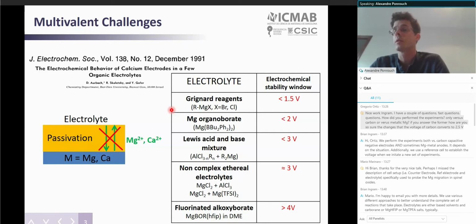And since the first generation of magnesium-based electrolytes, based on Grignard reagents, there's been a huge improvement, mostly in terms of electrochemical stability window, so we are now over 4 volts. Unfortunately, at the time, there was no calcium equivalent for these non-passivation film forming electrolytes, so the calcium-based chemistry was basically abandoned.